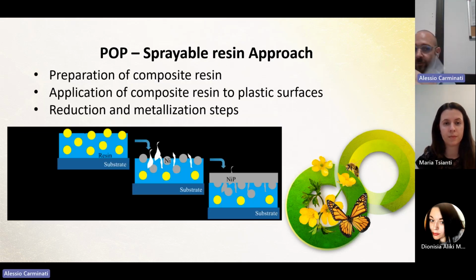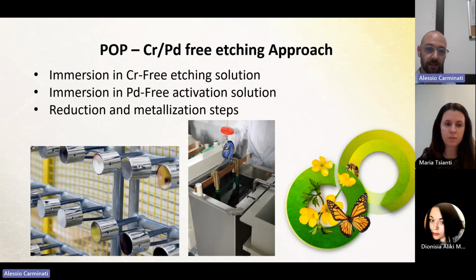So the output of this kind of process is the inclusion, in both cases, of metal particles that will catalyze the reaction of electroless nickel on the surface, and then the further plating of the other metals on the surface. And this is the kind of racks and plating equipment that will be used inside the project.